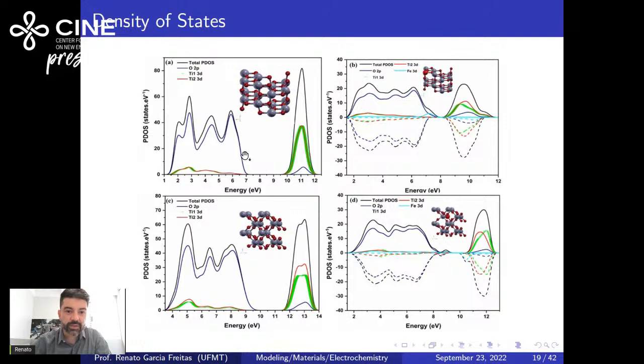So we have here the PDOS, as it's possible to observe, a large contribution of oxygen in the valence band, and in the conduction band titanium. You see we have titanium 1 and 2, I mean the first layer of titanium and the second layer of titanium here, almost the same, and we have the doping of iron here. We have the split because we have unpaired electrons, like Hund's rule, and we have oxygen with more contribution in the valence band, and titanium with more contribution in the conduction band.